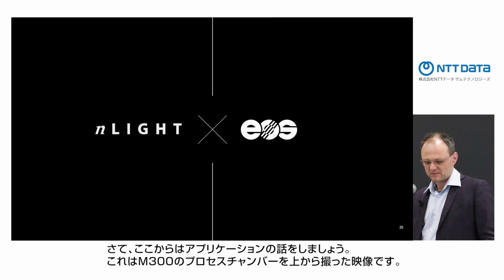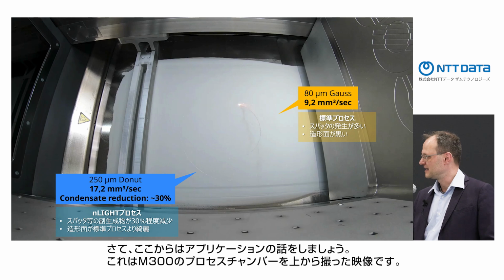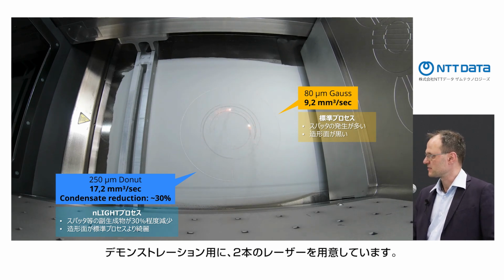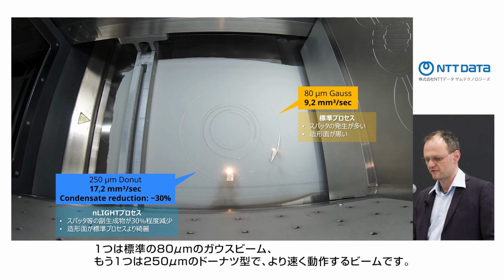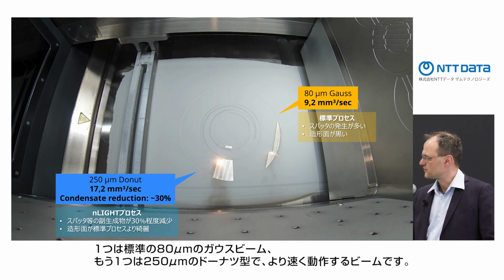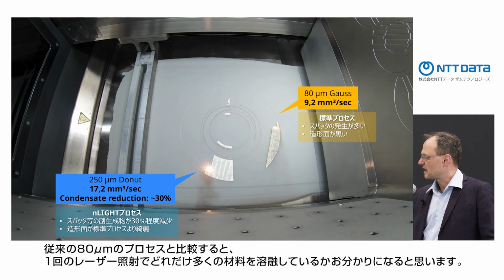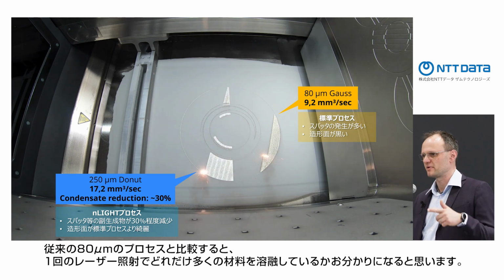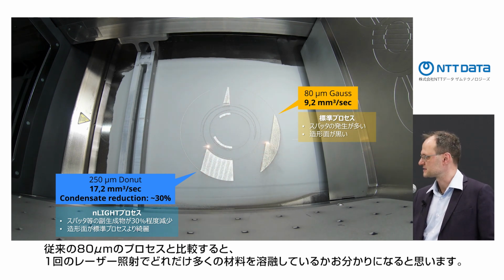But now I want to go into the exciting part, which is, of course, the applications. So here you can see the top view of our M300 process chamber. And inside this M300 process chamber, just for demonstrational purposes, we have one laser operating with the standard 80 micron Gauss, and the other laser with the 250 micron donut beam shape at a much higher pace. Now you can see how much more material is being melted per time by one laser in direct comparison to the 80 micron existing process.